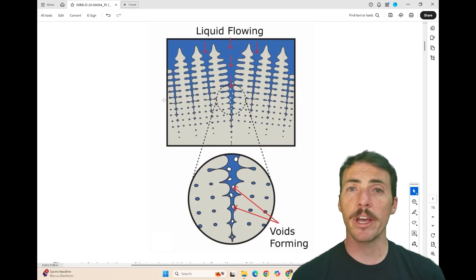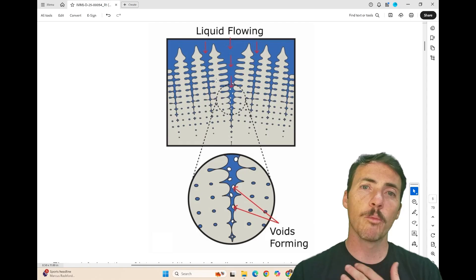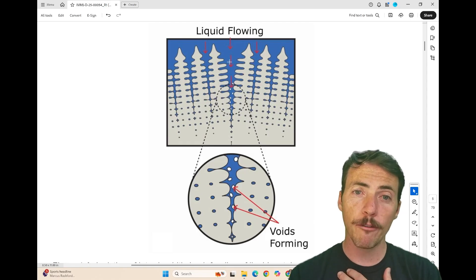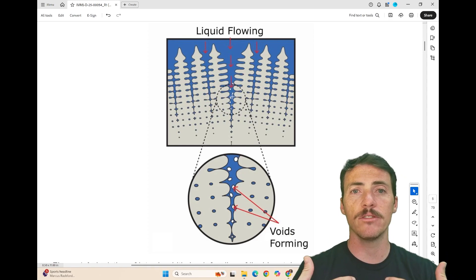Metals typically shrink upon cooling as they solidify, typically something like two to six percent, and so you have these solidified regions shown in light gray here growing in dendrites outward, and we're relying on the liquid metal flowing into these interdendritic regions to backfill the space during solidification.